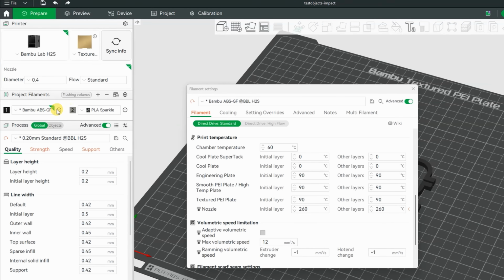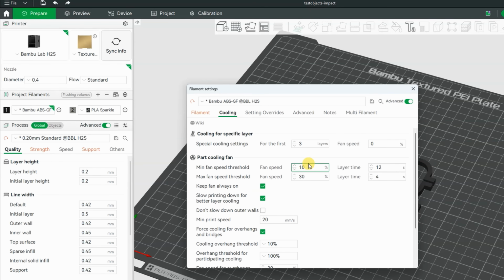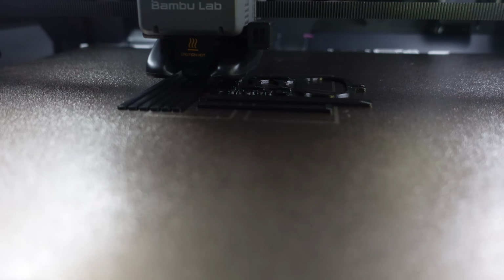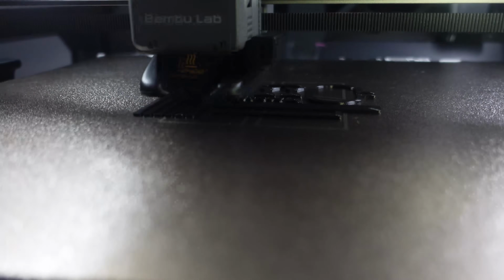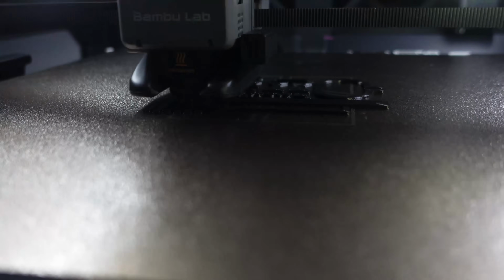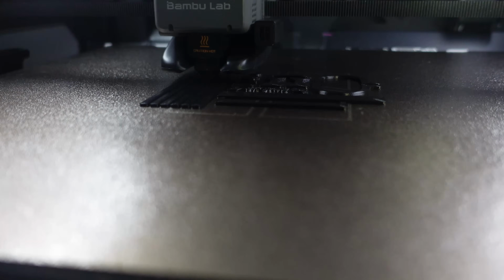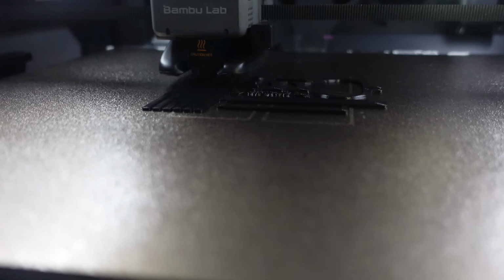Starting with the Bambu Lab ABS-GF profile: 60 chamber temperature, 90 on the bed, 260 on the nozzle, 12 maximal flow, and the part cooling maximal 30%. The start is great, absolutely no signs of warping, and of course the actively heated chamber and glass fibers will prevent this. Now, minimally, but I can feel that smell of the ABS.